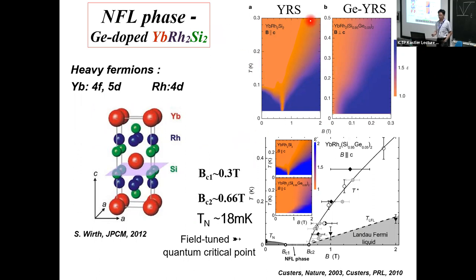If you dope this YRS with germanium, you will see an extended region in terms of the field, where the Néel temperature is going down to zero. But before the heavy Fermi liquid forms, there is a finite range in this field where there's no magnetic long range order. And at the same time, the T-linear resistivity persists all the way down to zero temperature. So this is another exotic strange metal phase.